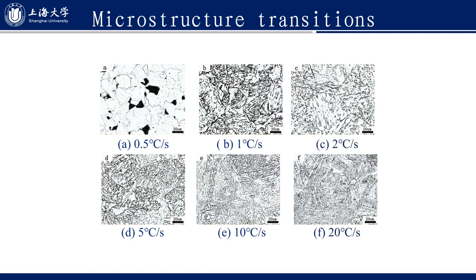With a cooling rate of 0.5 degrees C per second, the microstructure is mainly ferrite, and a small amount of pearlite occurs. Between 1 degree C per second and 10 degrees C per second, the steel obtained granular bainite microstructure. For cooling rates in excess of 10 degrees per second, the microstructure is a mixture of bainite and martensite.